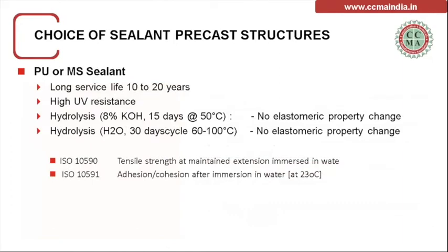What kind of sealant is generally chosen is either single part polyurethane or silyl terminated polyether MS sealants. Both are good enough to get into the specification of a precast building. So in nutshell, as bullet points, they look for a service life of a minimum of 10 years. Anything greater than that, if high-end sealants are accepted, up to 20 years is good, and that needs to be substantiated with the standards for the life of the sealant.